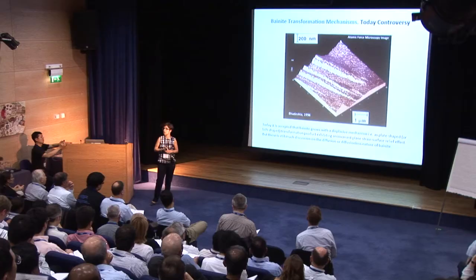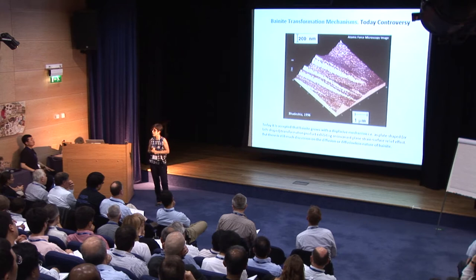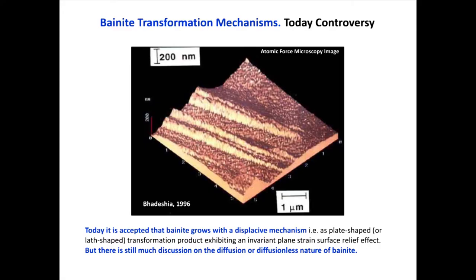If you read the literature nowadays, you can find again two different explanations. You can read that bainite ferrite grows supersaturated in carbon, and after that plate of bainite ferrite is formed, the carbon will partition into the austenite, or can precipitate inside the bainite ferrite plate at lower temperature, forming what we know as lower bainite — that is the diffusion-less explanation. But you can also read that bainite ferrite growth is a carbon-diffusion controlled process, and if we have precipitation during the reaction, cementite will precipitate at the austenite-ferrite interface as it moves.